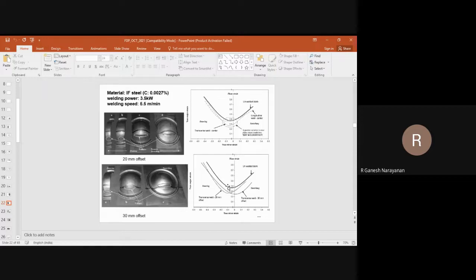Okay, it has to be away from that particular location, because the weld itself is a critical region, where properties are going to be significantly different. Now if you put the weld near a failure location, there are more chances that the component can fail a little early. That is very, very important. That's what this is going to tell you. The lab scale formability study is going to tell you that the 30 mm offset, which is very critical, is going to affect the forming limit.